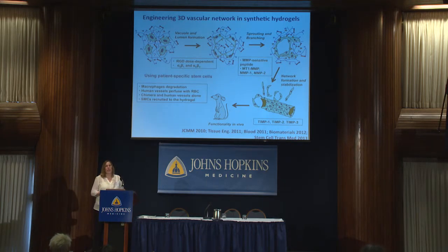all these studies, we actually demonstrated that we can introduce to this hydrogel specific adhesion molecules that are going to activate specific integrins, as well as degradation properties, so the cells will degrade the matrix, which allows them to form this lumen, and then stabilize into the vascular networks. We also show that when we transplant those, again, we're talking about human stem cells, into a host in different types of models, wound models, the vasculature is actually functioning, meaning that we will see flow from the host blood into the human vasculature.